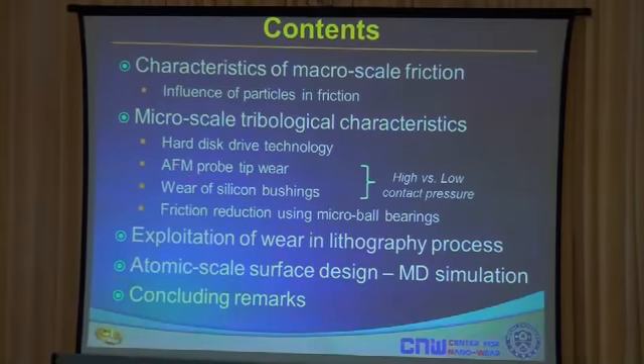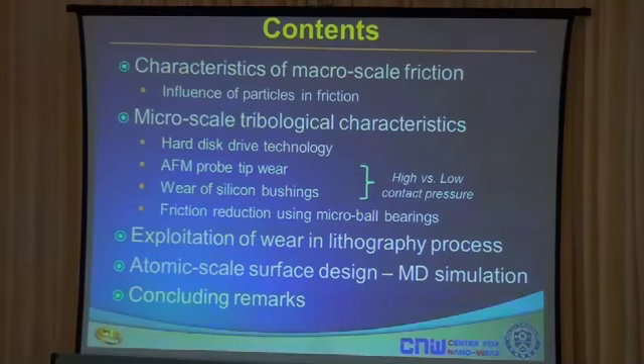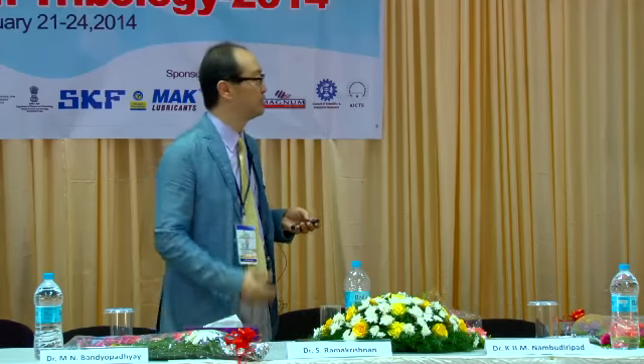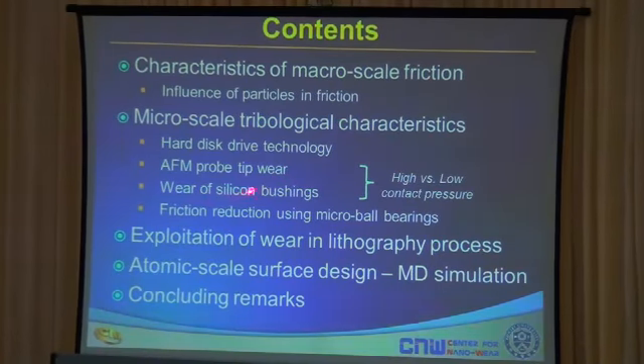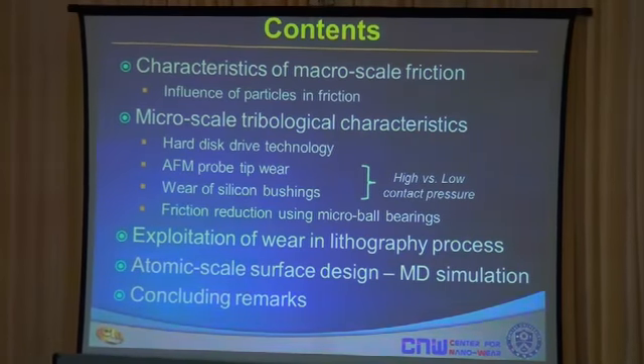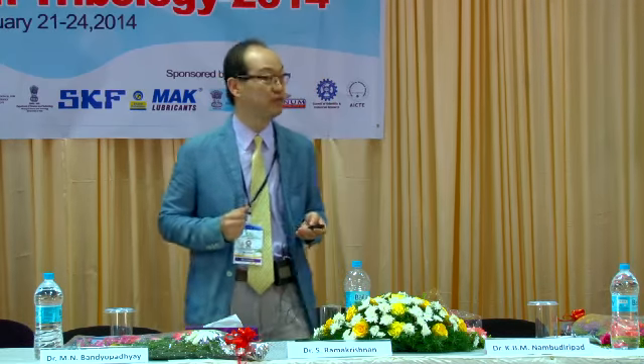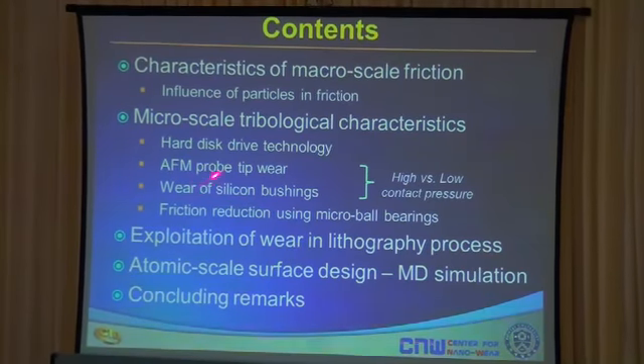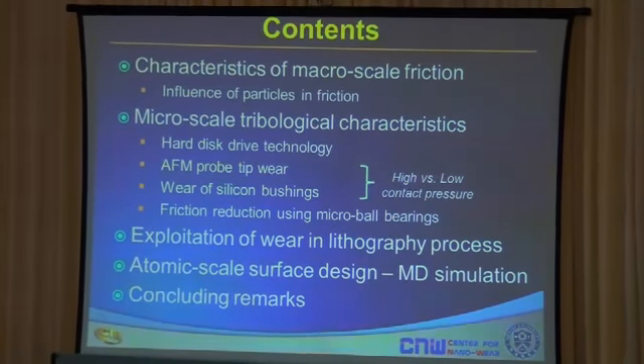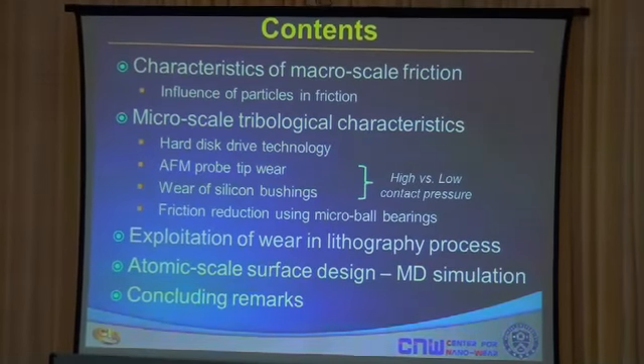Then I'd like to talk about atomic force microscopy, which is the most important tool used in nanotribology, and the wear associated with such devices, and talk about silicon bushings, which are used in MEMS to reduce the contact area to reduce stiction, and discuss the wear of these components. Basically, the AFM probe tip and the silicon bushing represent high versus low contact pressure for silicon-based materials. And I'll tell you that despite the fact the materials are similar, you have very different behavior in wear because of the level of contact pressure.